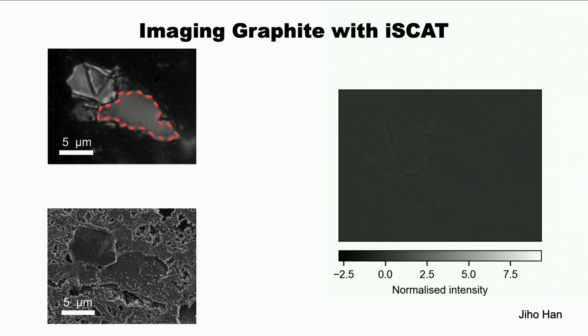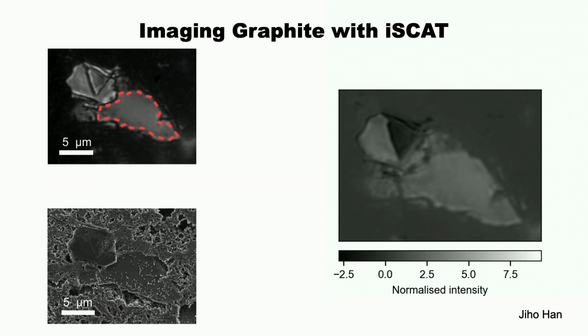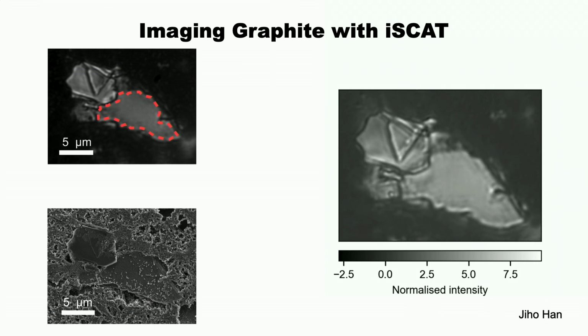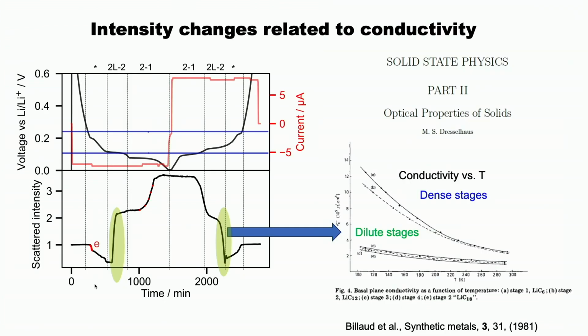So let's just look at what that graphite is. This is the iSCAT image. This is the SEM. You look at that particle and you think it's actually a pretty single-grain material, but when you unpick it like this, there are multiple domains within it. So what can we actually do with this iSCAT for graphite? Millie, in her solid state physics course for the MIT undergraduates, nicely explained what's going on here. You've got a dramatic change in the conductivity as you go from the dilute stage to the dense stages. So the conductivity goes up, and so the polarizability changes, and you get this very large change in the scattering, and that's exactly what you're seeing here.